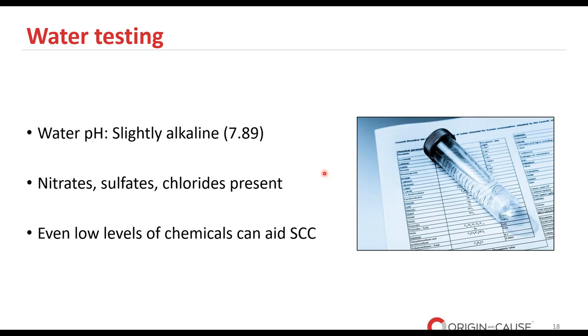Moreover, our tests also detected a number of compounds, specifically nitrates, sulfates, and chlorides, and these were all present in the water. Each of these, especially chlorides, have been associated with promoting SCC in certain metallic materials. But it's crucial to underline that when it comes to stress corrosion cracking, even low levels of chemicals can aid in the corrosion process. The cumulative effect of these chemicals, combined with stress, can significantly amplify the risk of stress corrosion cracking. So these findings, in essence, highlight the multifaceted nature of stress corrosion cracking, where both material properties and environmental factors play important roles.